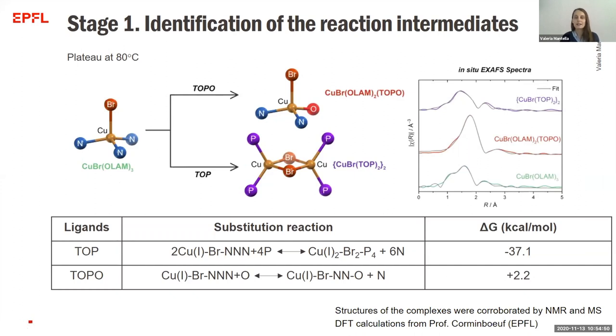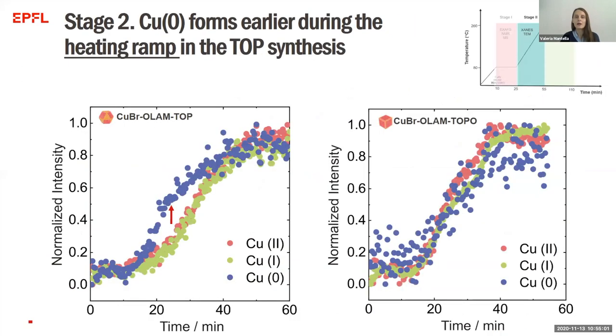So once we have identified this reaction mechanism, these copper one complexes, then we follow their evolution during the second stage, during the heating ramp, where a disproportionation reaction is occurring during both syntheses, with TOP and with TOPO. However, it's only during the synthesis with TOP that we can see in the collected XANES spectra that the signal of copper zero increases faster compared to copper one and copper two.